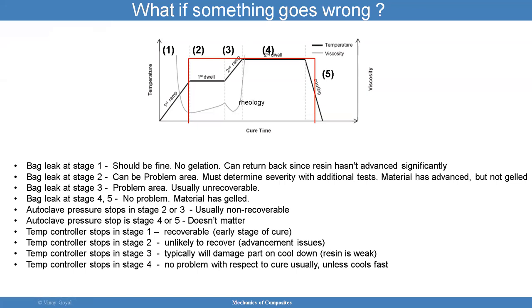The autoclave, say pressure stops in stage two or three. So if the pressure of the autoclave stops here, you may have a problem, usually non-recoverable. If the autoclave pressure stops at stage four or five, that's a little bit better. It doesn't matter anymore because consolidation was supposed to happen over here in this one through three. So the pressure again is there to help us out.